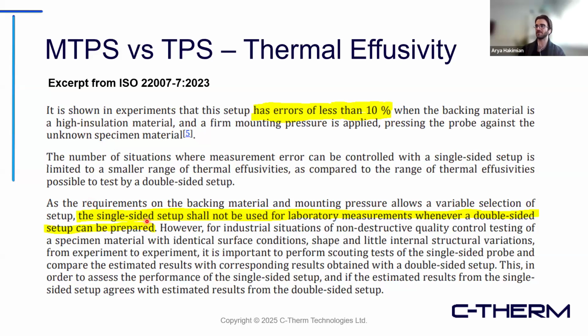But there's some general verbiage here on, ideally you're going to use the double-sided method because that's what gives you your best possible output. But for a lot of the effusivity side of things, there's discussion around the single-sided setup. Again, it's something that can be done, but understanding some of the differences and limitations there, I think it's important for folks to know about. And the big one here is it does not conform to the ASTM standard. So, just keep that in mind. Depending on what you're looking to get out of your measurement, if it's more for internal R&D, for product validation, or if you're looking to conform to a specific standard, these different things can play a role in which method is really going to be the best fit for you at that given time.